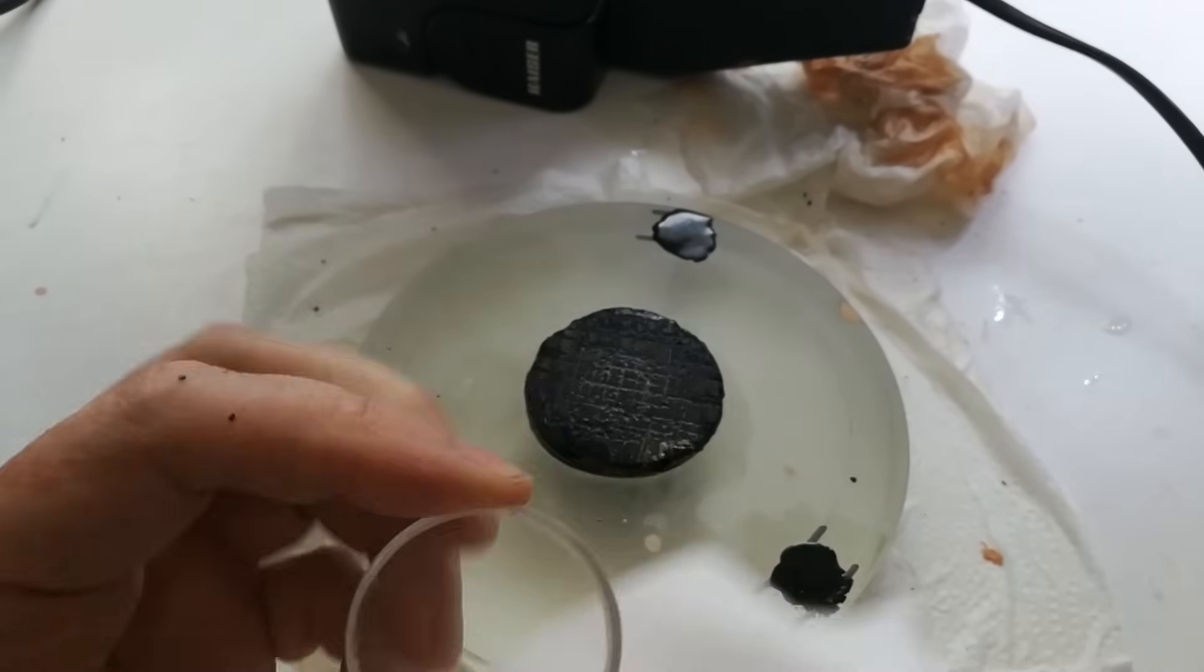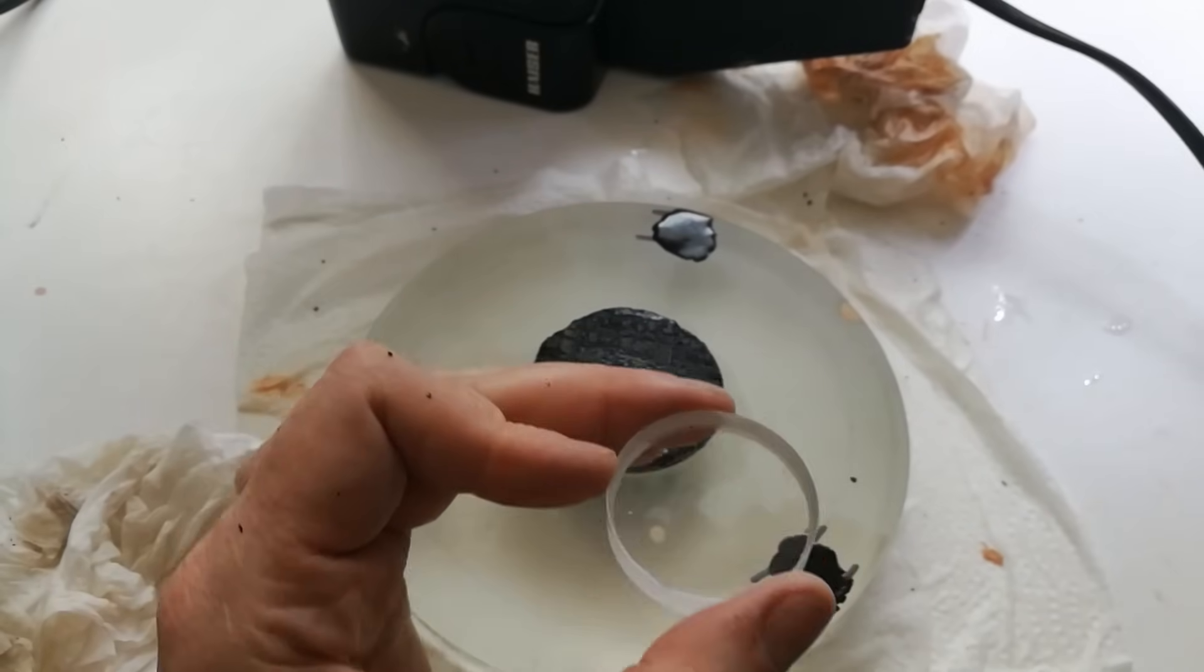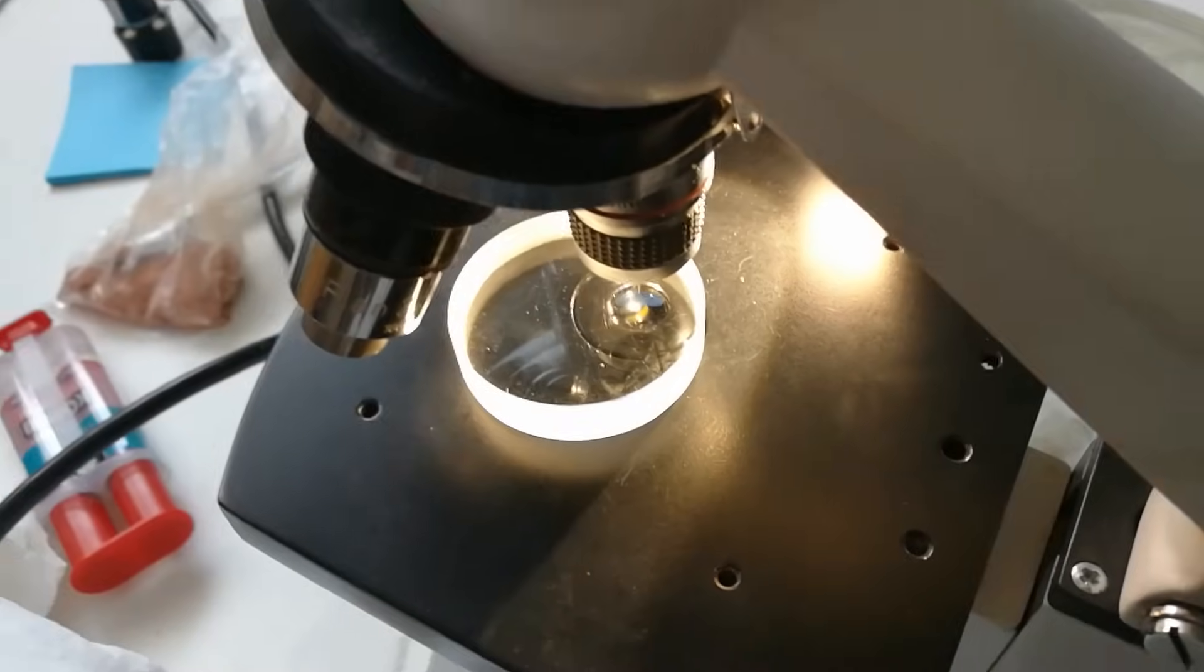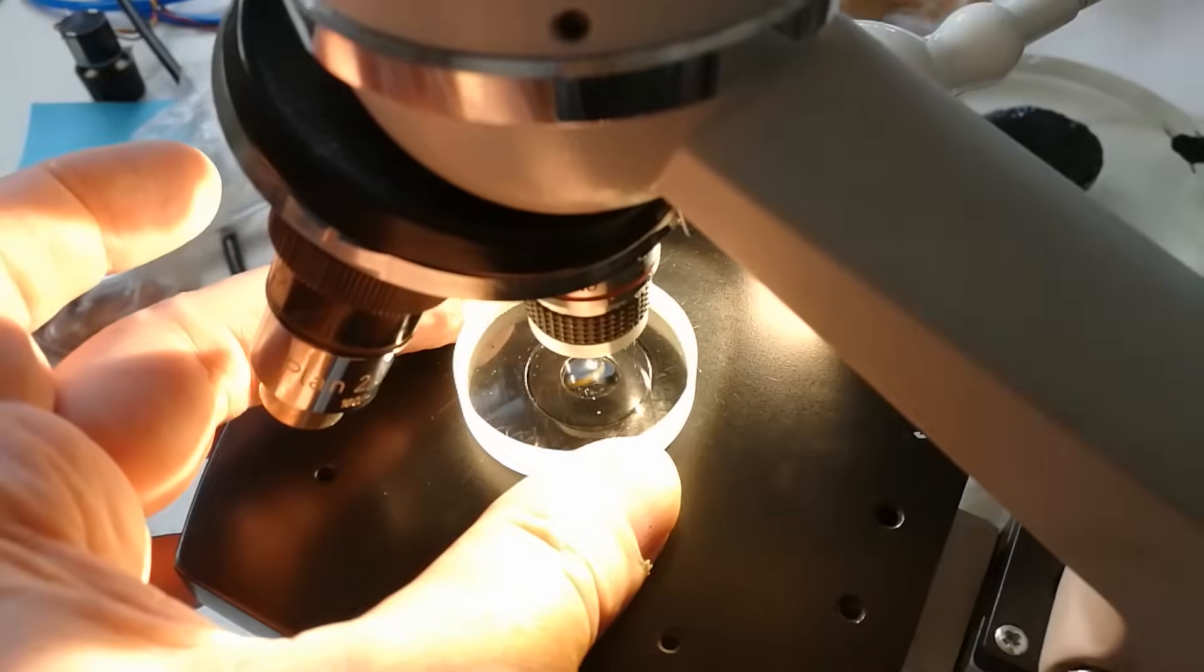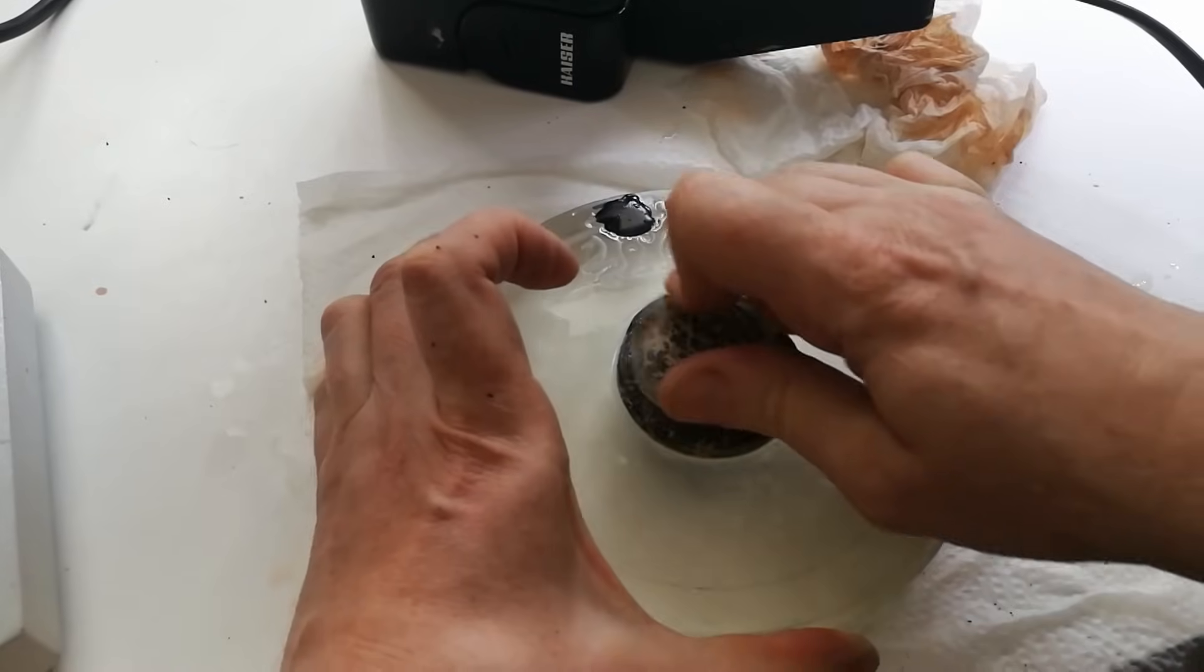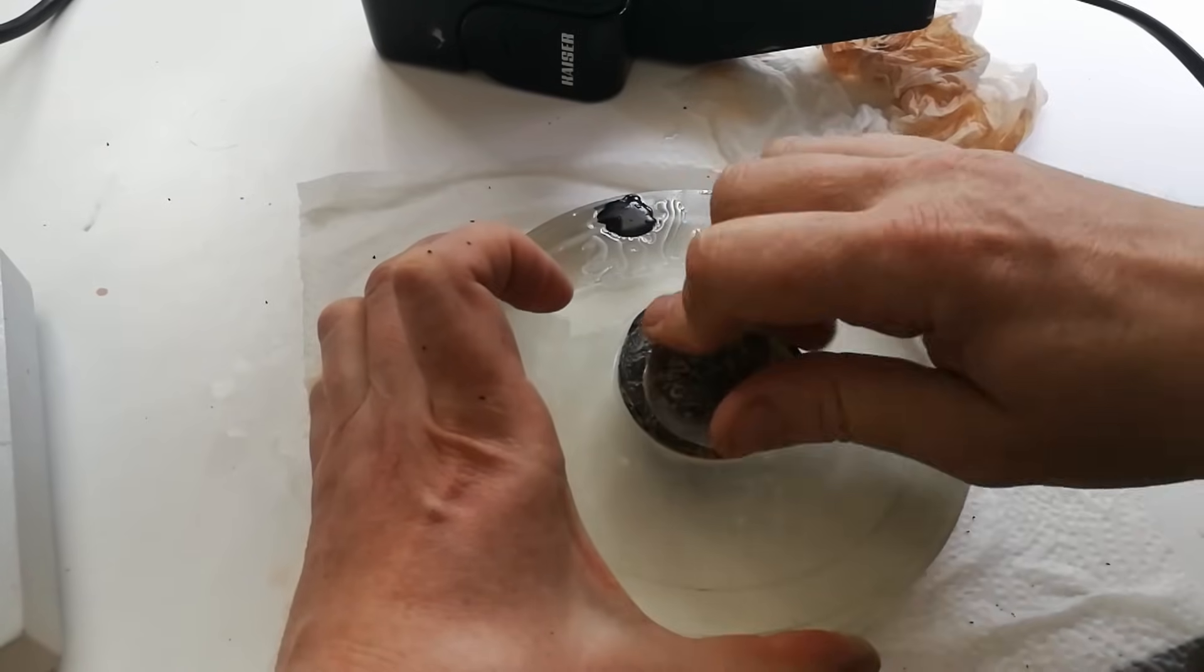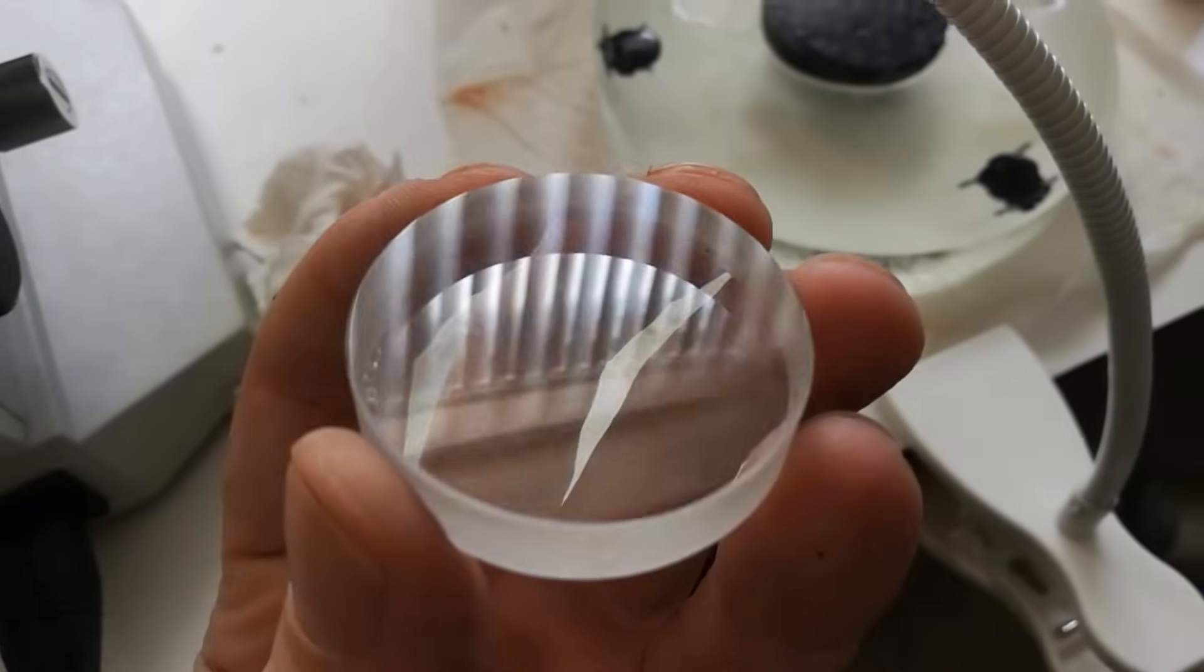So this is the result after about 15 minutes of polishing. It already looks pretty good by visual inspection, but under the microscope we can still observe some small pits in the surface. So we need to continue until even the last of these grinding pits has disappeared. This is the case after approximately 35 minutes. We end up with a very nice shiny surface.